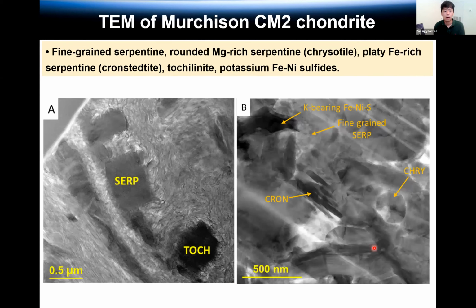Now let's move to more TEM images of the Murchison carbonaceous chondrite. This is a TEM image of serpentine and tochilinite, also interacting with the very fine-grained serpentine matrix. Actually, in this texture, some serpentine and tochilinite preserve the pre-existing mineral phases. So this texture indicates this Murchison carbonaceous chondrite experienced quite an extensive aqueous alteration process.